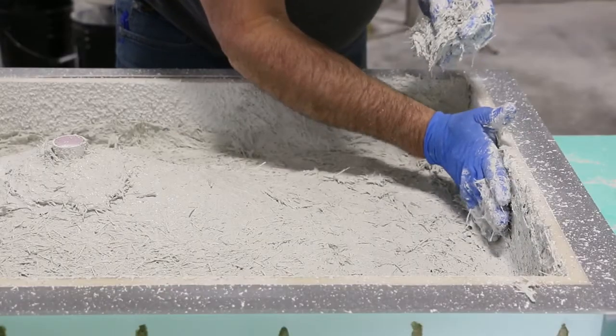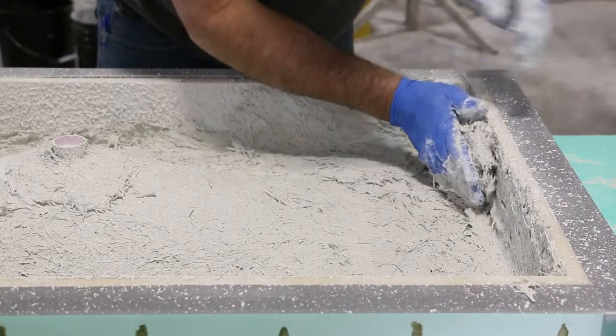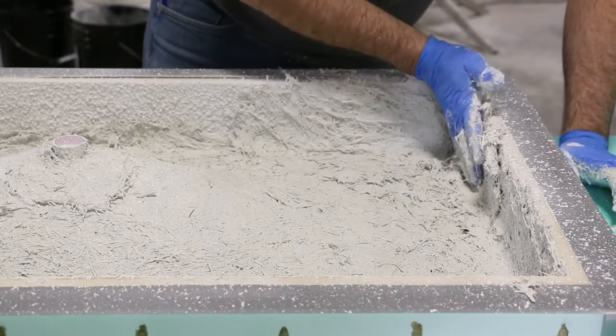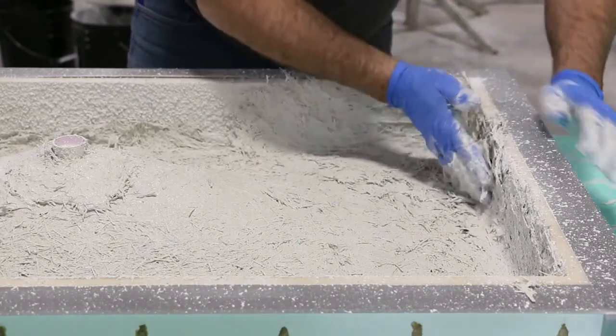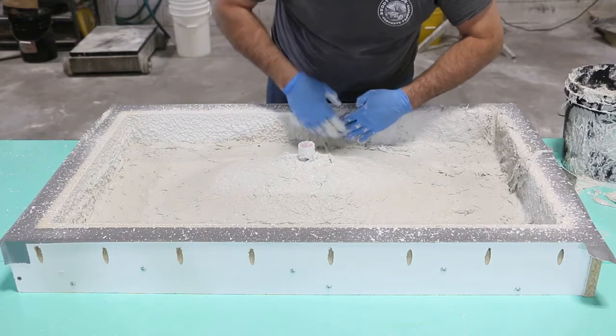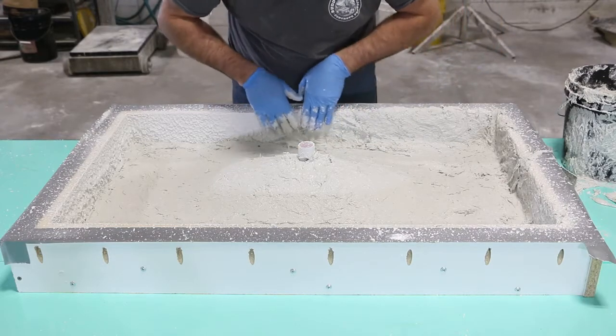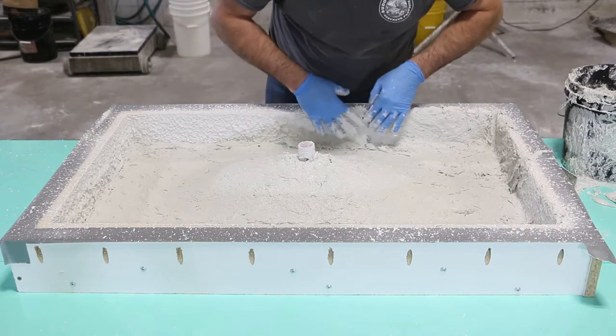Continue applying the material until the entire surface has been covered. It is important to execute this step as diligently and quickly as possible, so as not to allow the face coat to dry, which may cause delamination between the two layers.